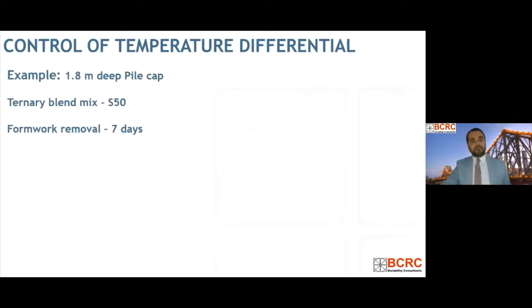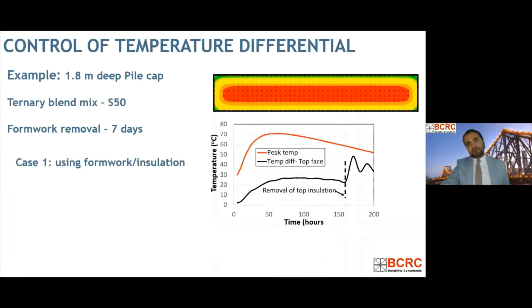This is an example where we have a 1.8 meters deep pile cap, cast using a ternary blend mix S50, and the proposed formwork removal time is 7 days. In the first case, we will consider using the formwork or insulation. This is the thermal modeling outcome of this example. We can see the peak temperatures are around 70 degrees. The temperature differential, while the formwork was in place, is more or less near the allowable limit.